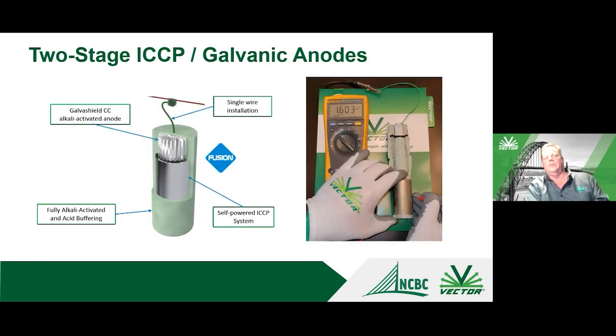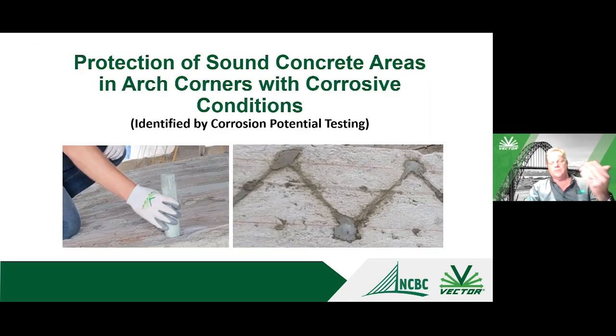Now, they also looked at what to do for the other areas which were currently sound, but were actively corroding. And how do you do that? You can actually utilize a technique that's called a corrosion potential survey, where you're effectively measuring the risk of corrosion in sound concrete by using a reference cell. Generally, it's a copper sulfate reference cell connected to a multimeter, which is connected into the reinforcing steel. So any areas where you do a corrosion potential survey and you're seeing that you have a high probability of active corrosion, but you still have sound concrete, that's an area where you can look at using other types of protection systems that are more proactive.